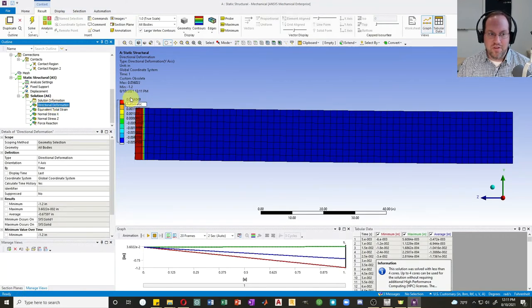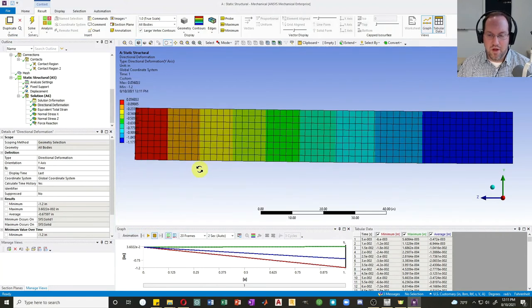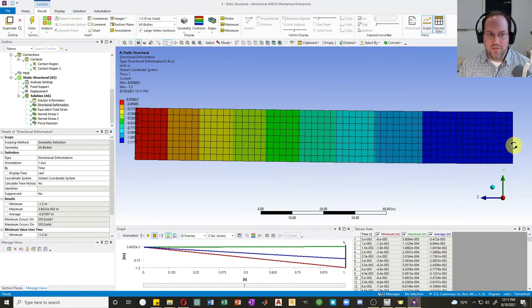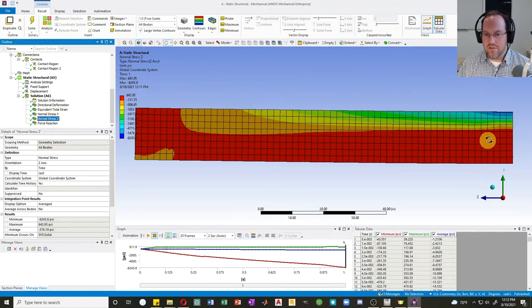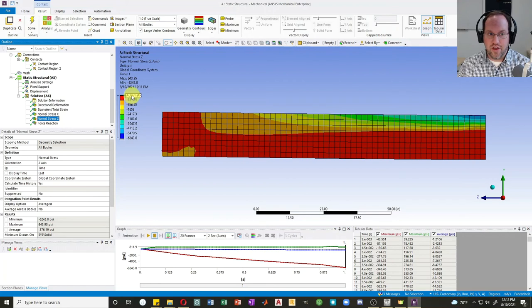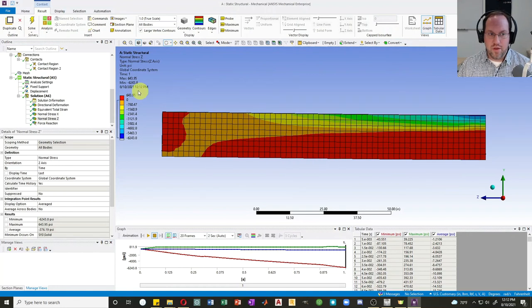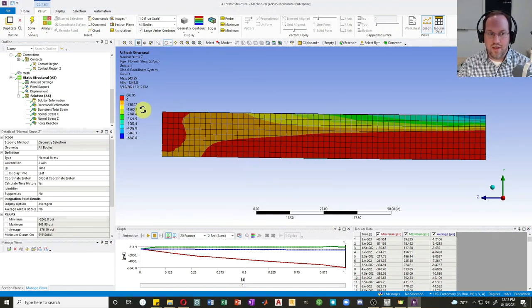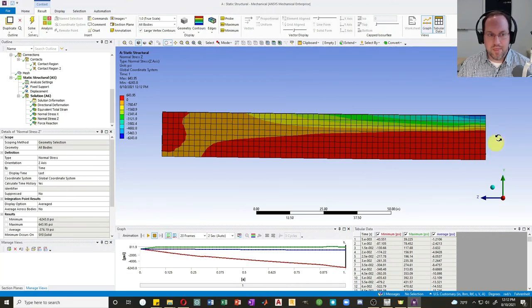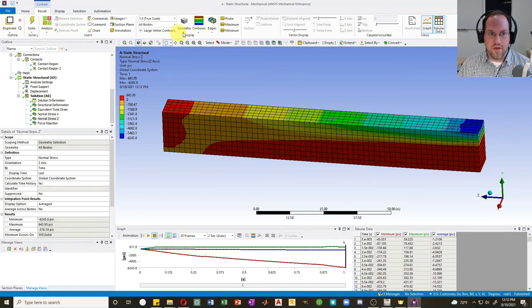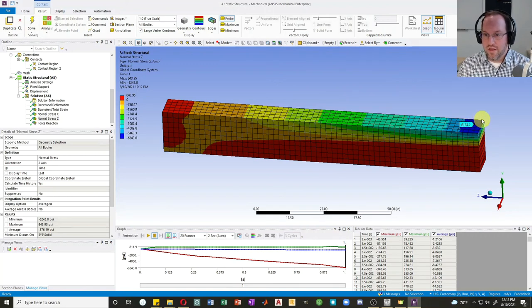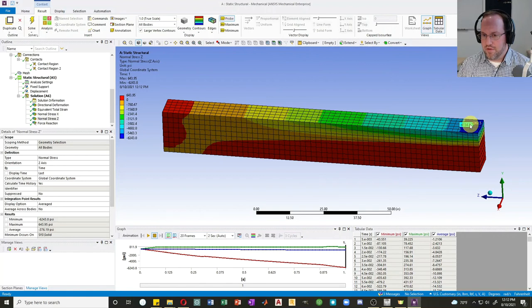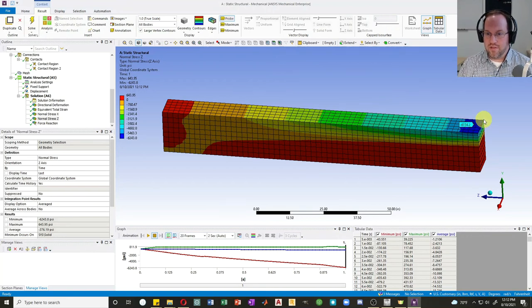We can also look at our normal stresses in the z direction. This can tell you your stresses within the concrete. One thing that I like to do is you can change the values on the scale. I like to turn one of these values to zero precisely so that we can see now anything that's red is in tension and then anything orange or different is in compression. We can see here is our compression and tension regions just as we'd expect. On top we can see this is effectively almost crushing. If I probe that we can see that it is actually over my compressive strength. That might be because of biaxial factors and things like that. There is some confinement due to the bearing pad, so it can reach a stress slightly higher than the 6,000 psi uniaxial strength.